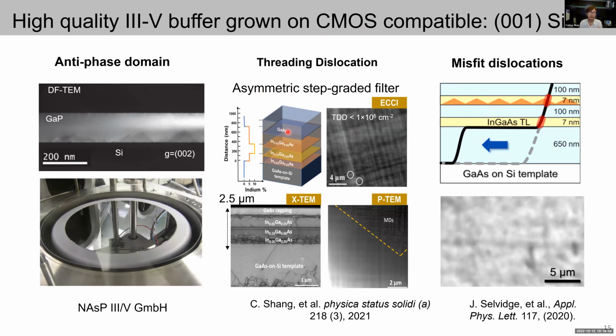With this kind of filter structure, a surface threading dislocation density as low as 1e6 can be achieved within just 2.5 micrometers of III-V layers. This is quite close to the theoretical limit, and it is quite trustable as it's verified by both electron channeling contrast imaging and plan-view transmission electron microscopy.